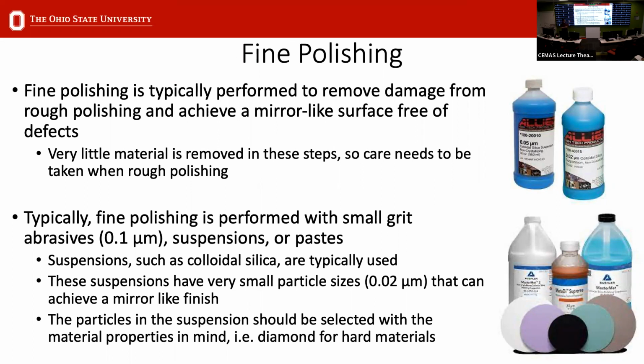So there are diamond based, and then one of the commonly used ones is colloidal silica, which is a suspension that has small silica particles of various diameters. So in my experience, I typically polish down to about 0.02 micron particle size to remove the damage from the previous layers and achieve a mirror-like finish. So these are great for removing very fine layers.